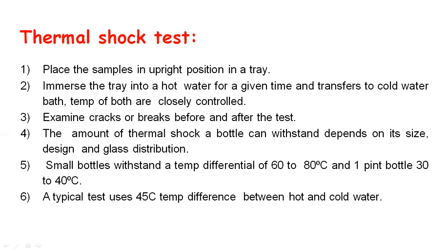Small bottles withstand a temperature differential of 60 to 80 degrees Celsius and one pint bottles 30 to 40 degrees Celsius. A typical test uses a 45 degrees Celsius temperature difference between hot and cold water.